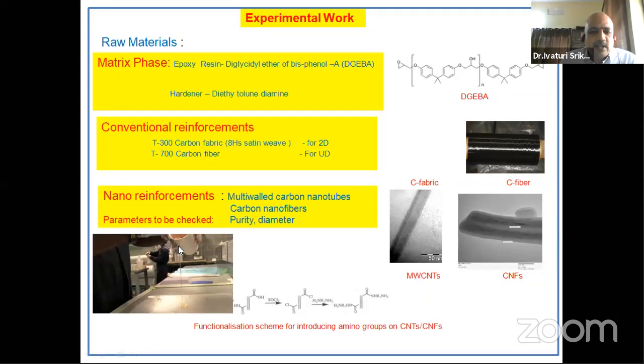This is a typical image, not our own image, for your understanding. I'm showing the liquid resin, in which we added our purified, functionalized, and dispersed CNTs. We have done the amine functionalization, then poured them onto the fabric layers. Then we laid up, and realized the composite laminates. This is called a 2D laminate, a two-dimensional fabric laid up.